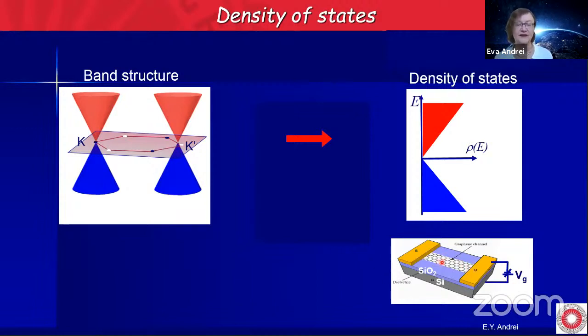We take a piece of graphene and we deposit it on silicon dioxide on a silicon wafer, which is made out of n-doped silicon, which is a conductor, and it has a thin layer, 300 nanometer thick, of insulator, silicon dioxide. Then you slap on 2 electrodes, a source and a drain, and then you connect a gate voltage to the silicon gate. So what you've created here is a capacitor. So when you change your gate voltage, you can either put electrons into your graphene or pull them out.